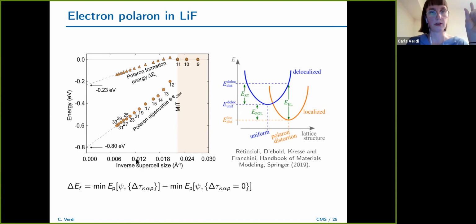There is a spurious interaction between defects in the supercell's replica. And so you actually need to extrapolate to infinite supercell size, which you can easily do because you do calculations at varying size and then you can linearly extrapolate. Another thing to notice is that you see this shaded region here with MIT written. MIT stands for metal insulator transition.